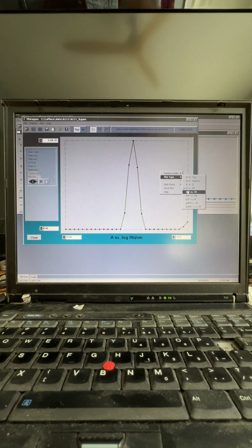You have to remember that the scattered intensity, these amplitudes are really the scattered intensity. These amplitudes are proportional to concentration times molecular weight times form factor. So if I do A over P, what I've got on the right side of the equation, A equals C M P. If I divide both sides by P, I have A over P on the left and I have CM on the right. CM is the sort of intrinsic scattering power of the system.